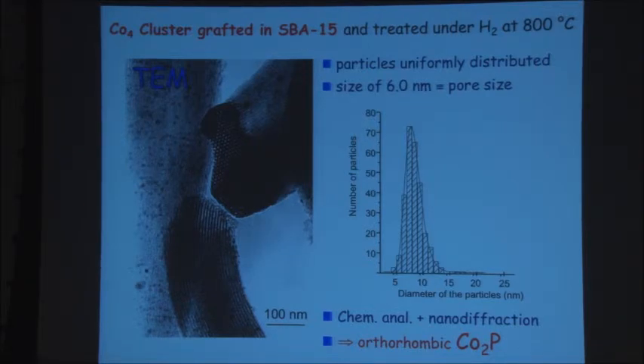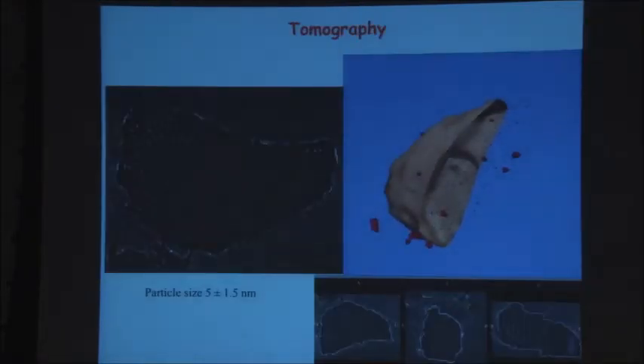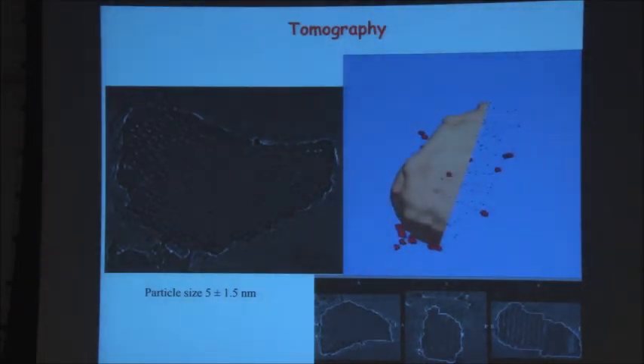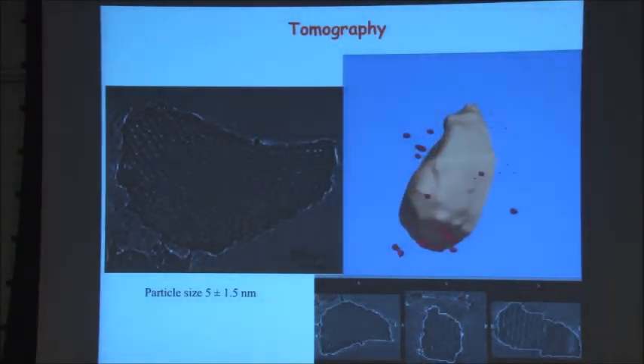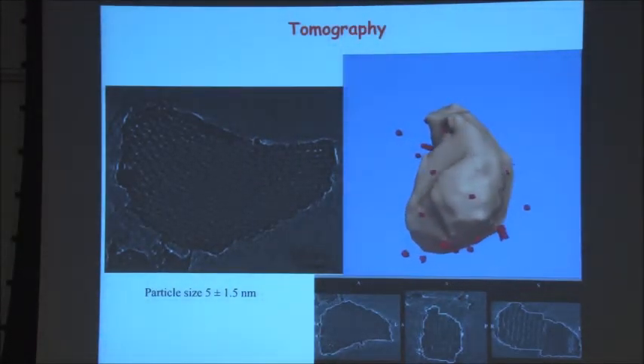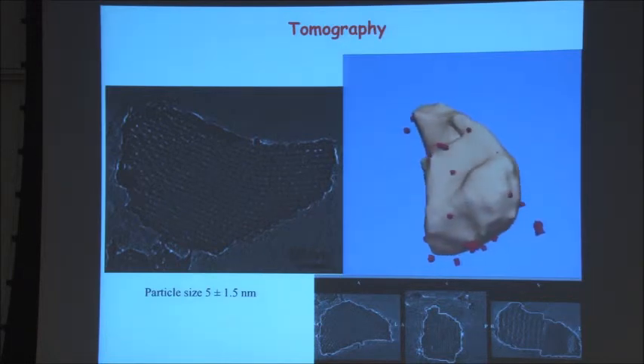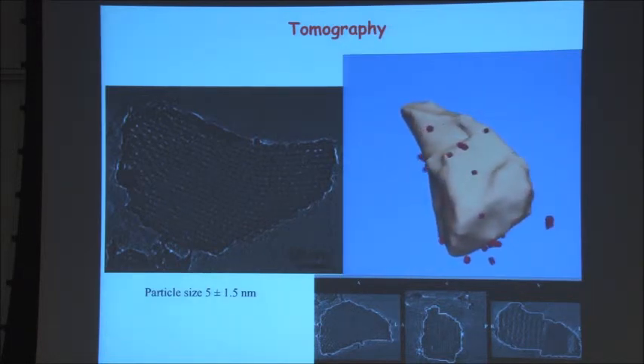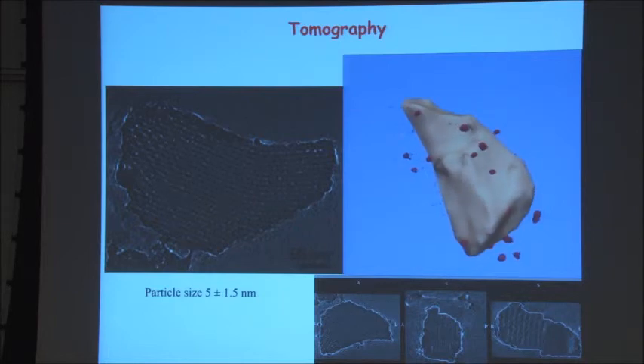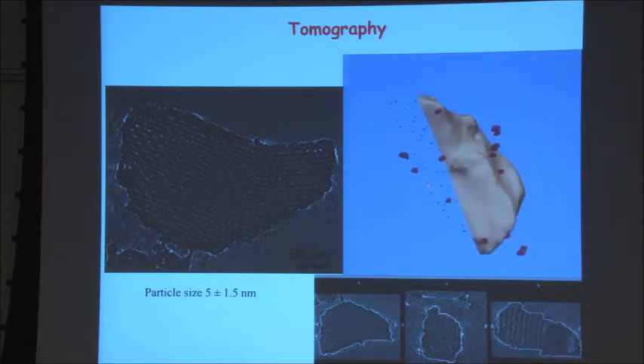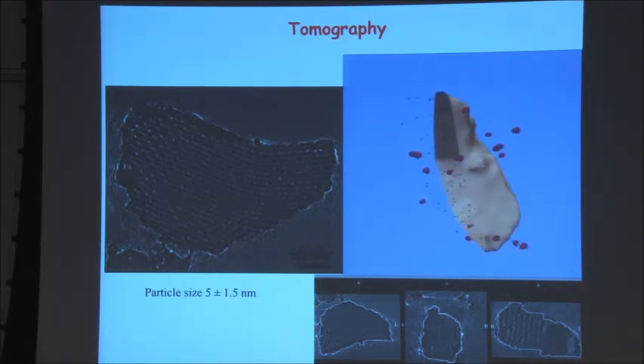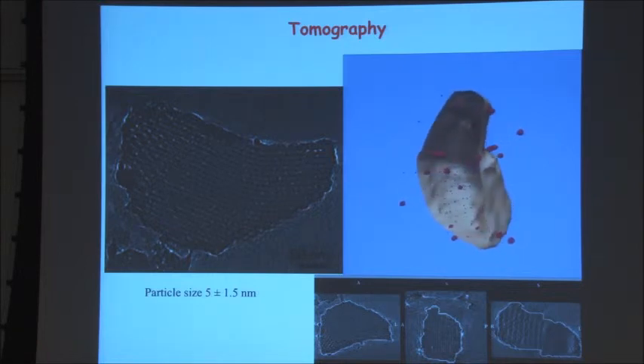Now, the fact that the particles are really inside the porous material is shown here by tomography. This is the cut of the support. The red dots are gold standards to have an evaluation of the size. But the little blue spots you see are the nanoparticles. They are really inside the cavity of the mesoporous materials and not outside.